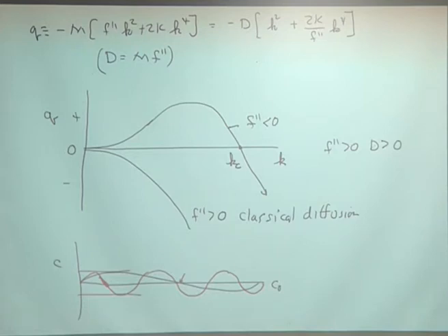So what happens is the energy goes up, and eventually the system says, I don't want these high wave number fluctuations or small wavelength fluctuations. So the system decays at large k. So it's due to this gradient energy effect. So basically the gradient energy effect, and what you'll see in the mathematics literature is that the gradient energy coefficient regularizes.